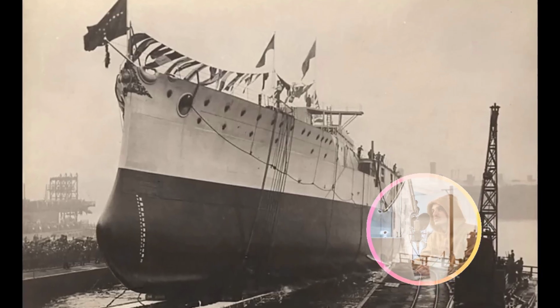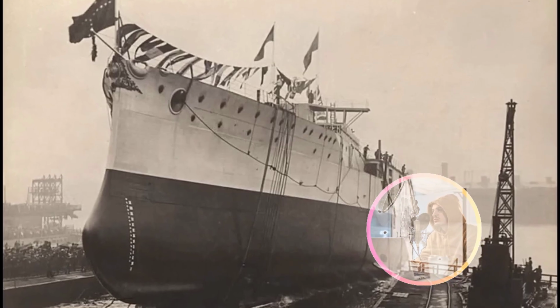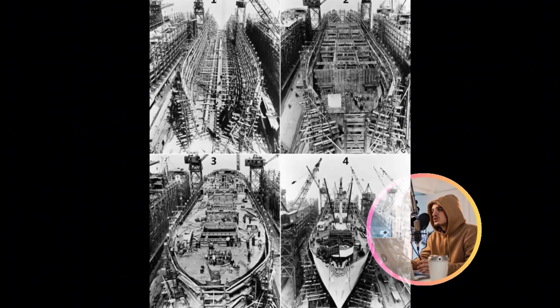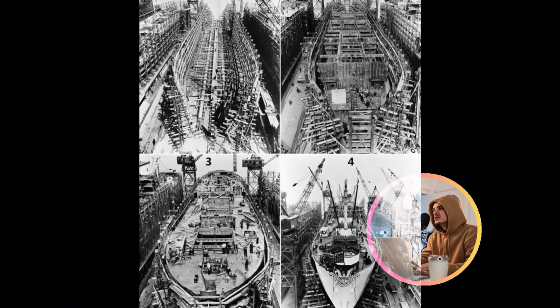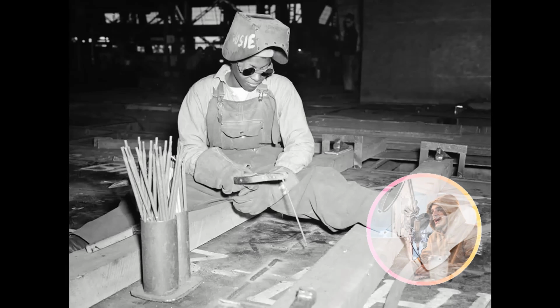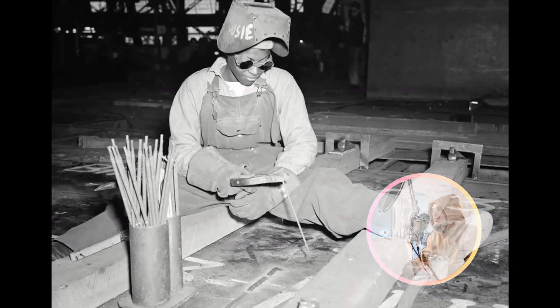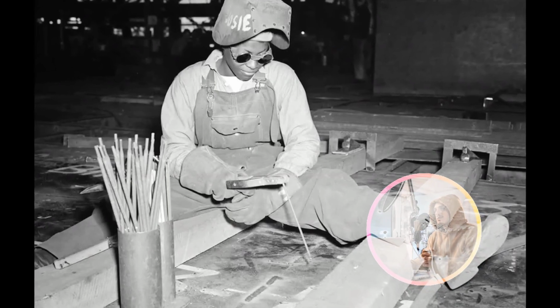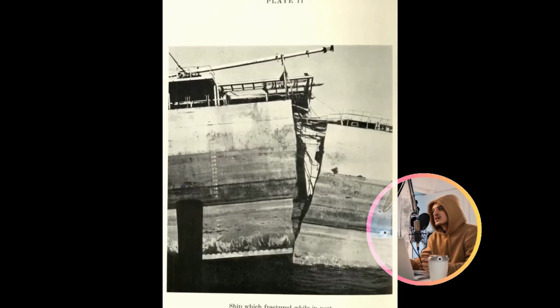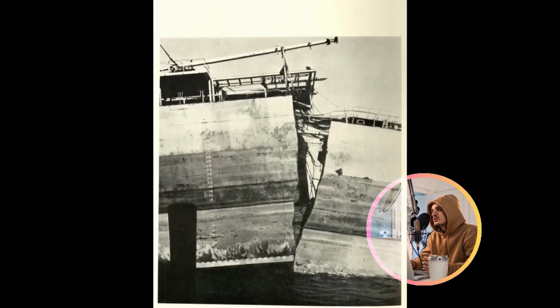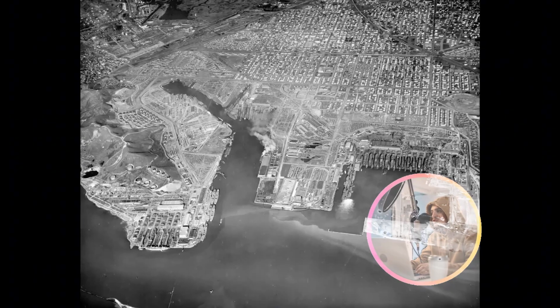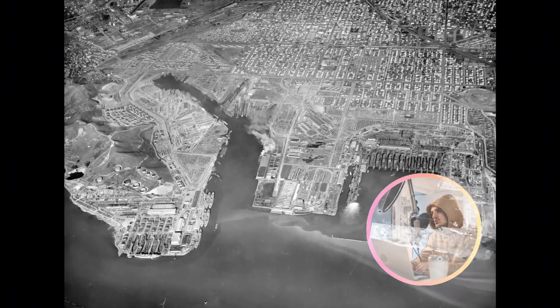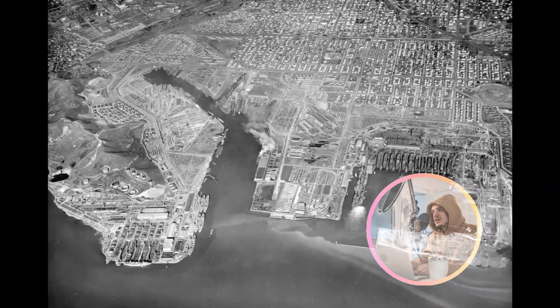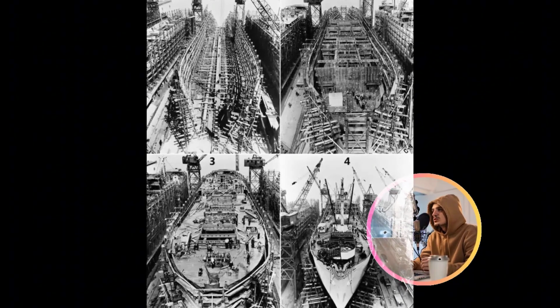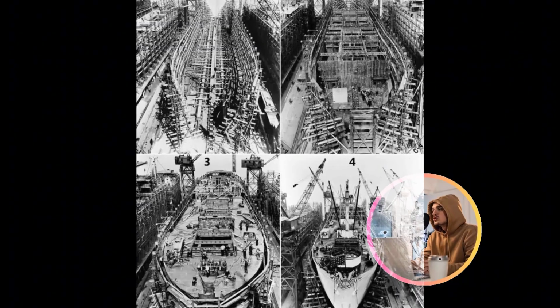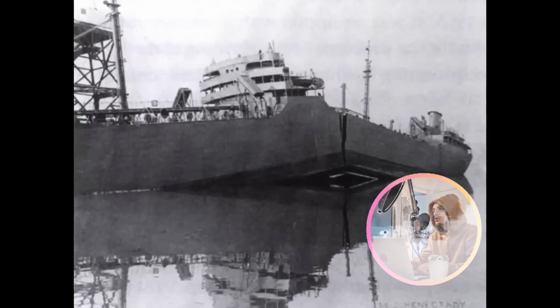The enhanced steel specification proved to be an absolutely pivotal development. This innovative alloy, officially designated as killed steel, due to the strategic addition of aluminum during its production process to meticulously eliminate oxygen, exhibited dramatically superior toughness, particularly in low-temperature environments. Rigorous laboratory analyses conclusively demonstrated that the critical transition temperature, the precise point at which steel undergoes a detrimental shift from ductile, flexible behavior to brittle, fracture-prone characteristics, had plummeted from approximately 40 degrees Fahrenheit in the steel utilized for Liberty ships to an impressive near 5 degrees.